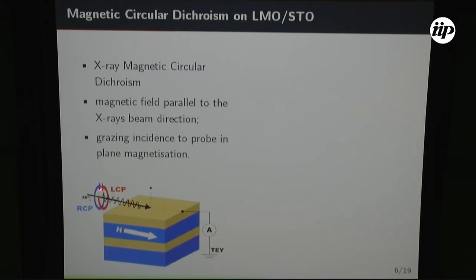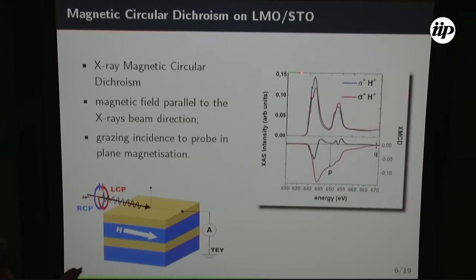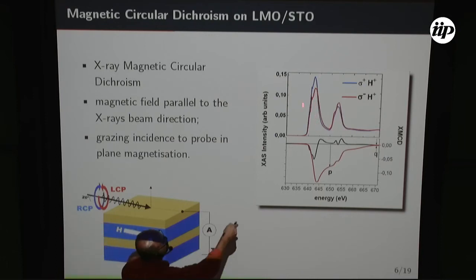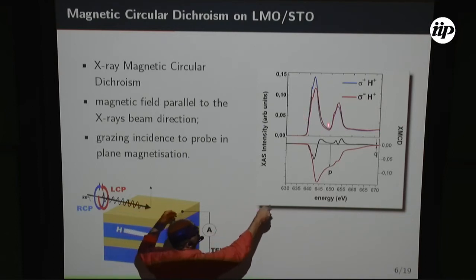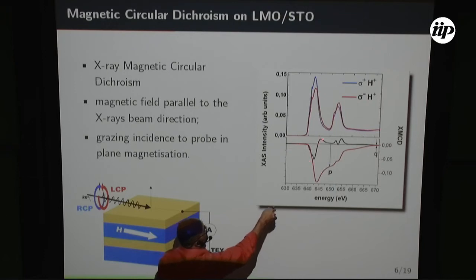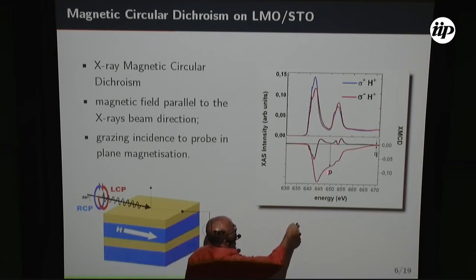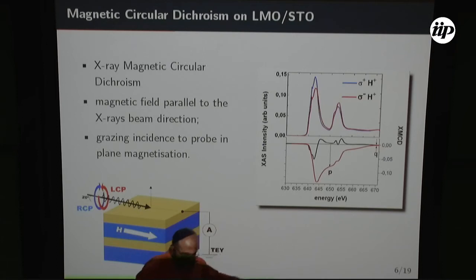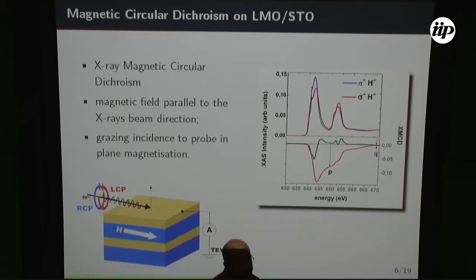Now, instead of linear, I'm going to measure with circular polarization. This is for the manganese again, and here you see the traditional circular dichroism. You have something that goes above in one edge, below in another. You see the difference signal here in black, and the integral here in red. The sum rules for dichroism don't hold for manganese or titanium, as I'm going to show you. But qualitatively, you can have information.